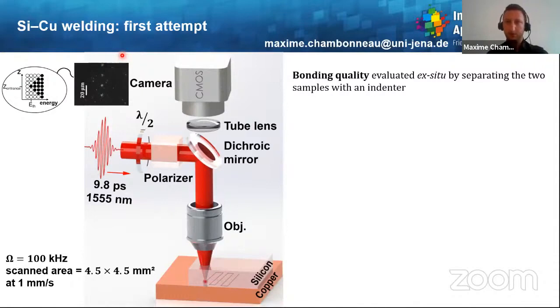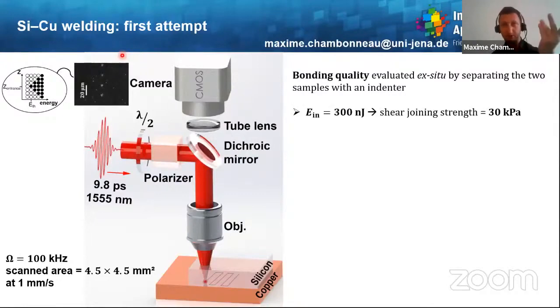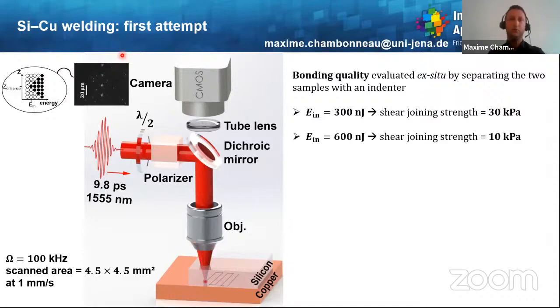Then we evaluate the bonding quality ex situ by separating the two samples with an indenter. So let us have a try. If we set the input pulse energy to 300 nanojoules, then we are able to measure a shear joining strength of around 30 kilopascal. Okay, good to know.